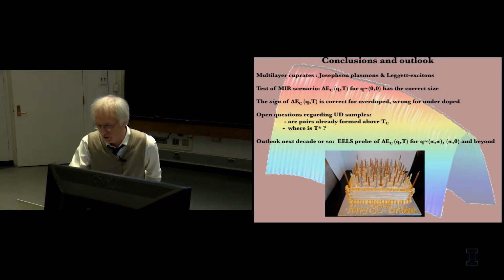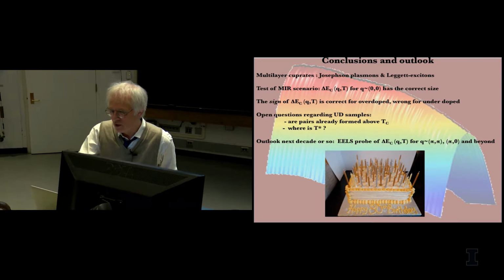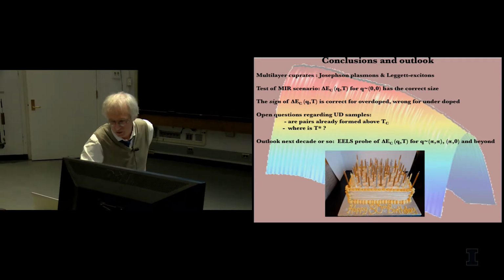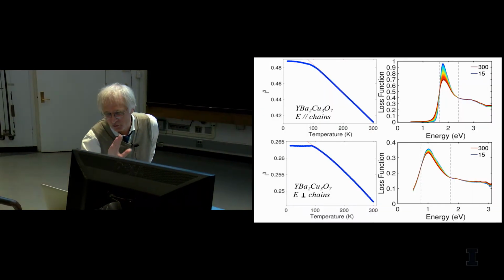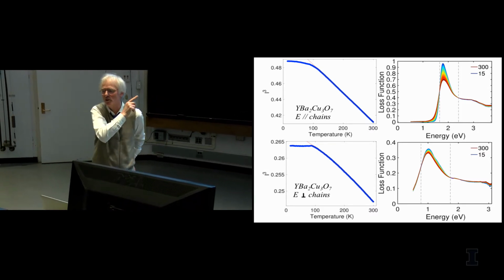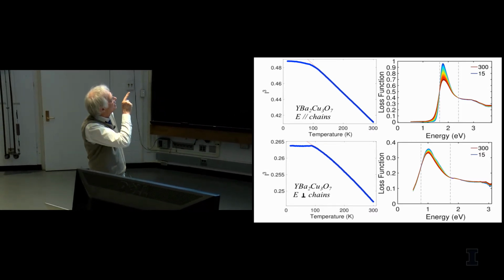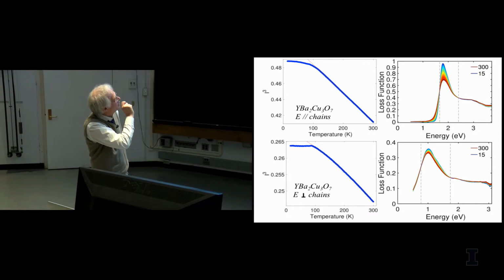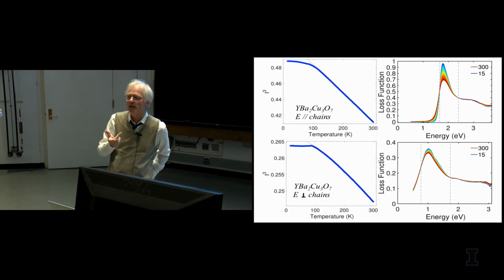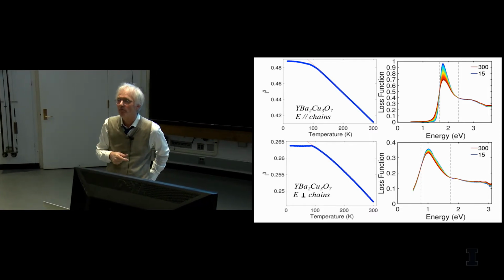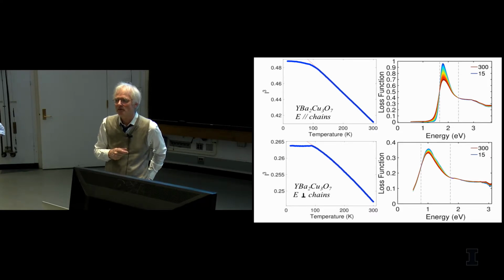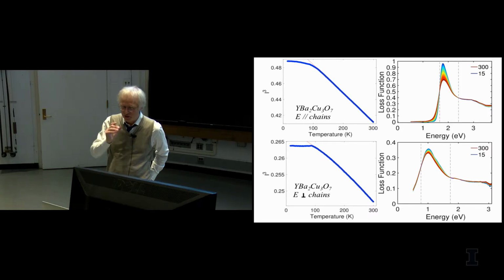This is already clear if you look at a graph like, oh, it's not here now anymore. I have one of the best ones here. It's actually one of the recent ones we used a few months ago by YBCO. Even there, you see a very nice kink, but I would say this is not more precise than 2 or 3 degrees. So it's that precise. But if you go through T star, in one of the underdoped ones, there's nothing, right? There is nothing.